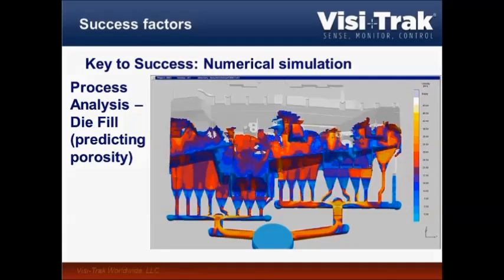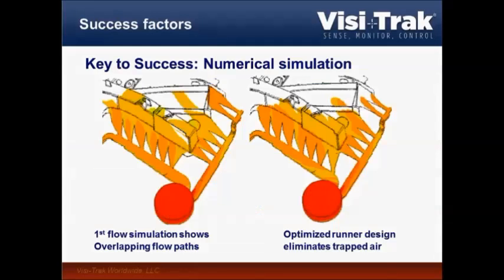We see here an example of a gating system. Some people call it the antler gating design because it looks a bit like that, but you can see the metal goes in over the entire front of the part. So with the simulation, you optimize your metal flows. Here in this case, in the first simulation we saw we had a metal front coming in here and another metal front coming in here, and these two metal fronts would come together and lock in air and dirt, because any metal front will push ahead all the dirt that's left in the cavity. That's why we want a homogeneous flow all the way through and push all the dirt into the overflows. That is also why you typically will find better properties on the inlet side than on the outlet side.